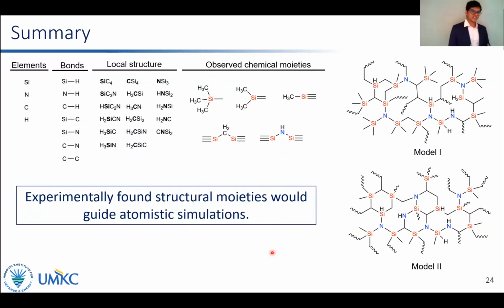Based on the structural moieties identified and gathered by various spectroscopic evidences, we put them together to synthesize a couple of abstract models. Model 1 represents a disordered material that is porous with more terminal methyl groups. Model 2 represents a film with a higher degree of cross-linking with fewer terminal methyl groups. We hope that the experimentally found structural moieties would guide atomistic simulations to generate better physically relevant models.